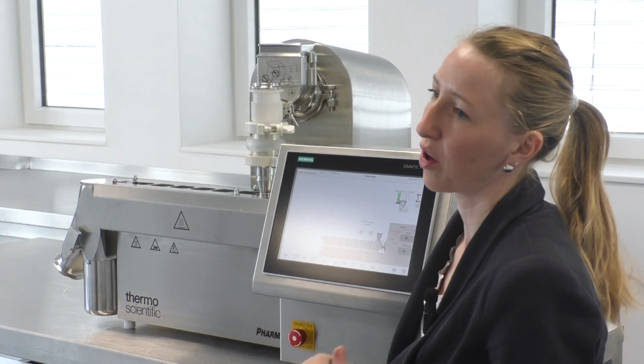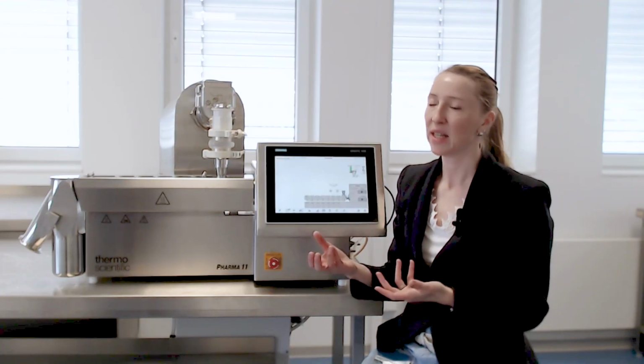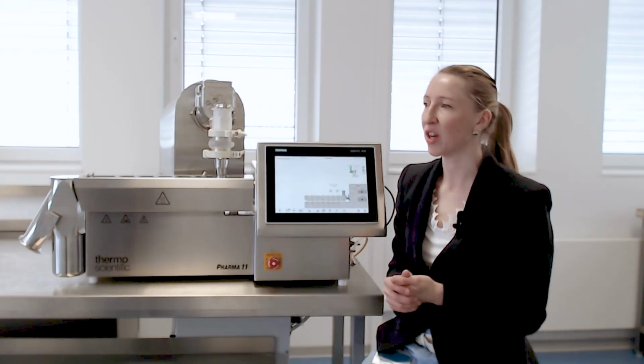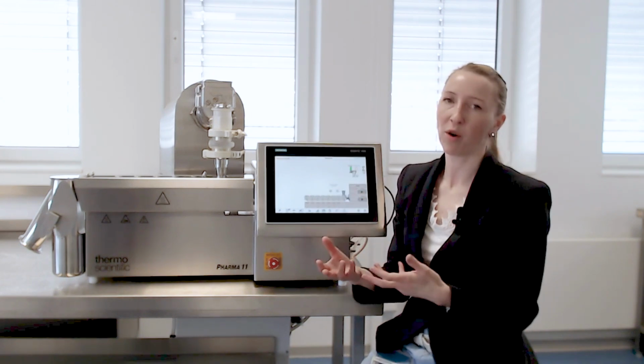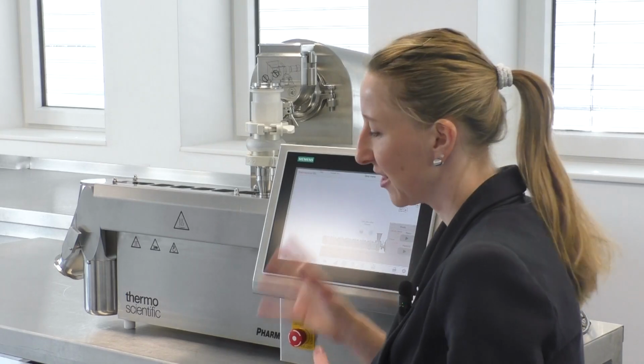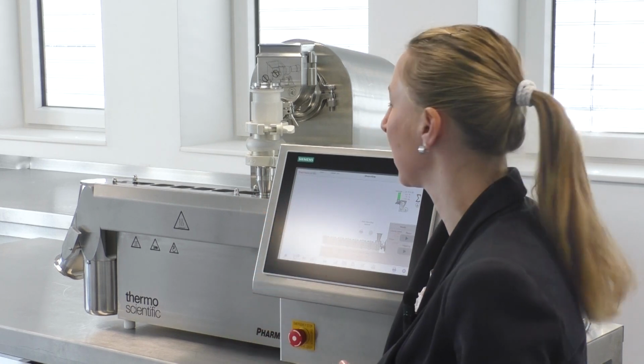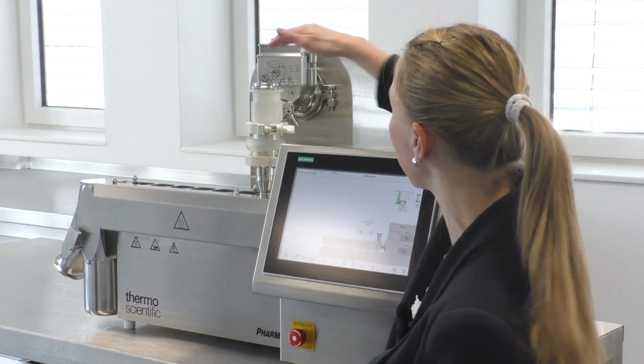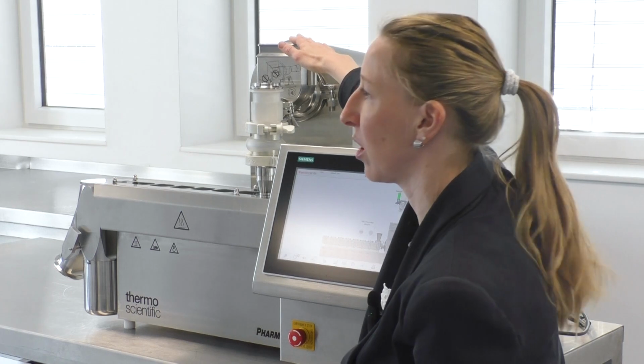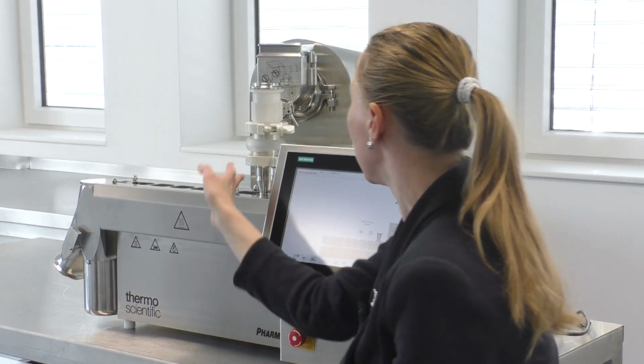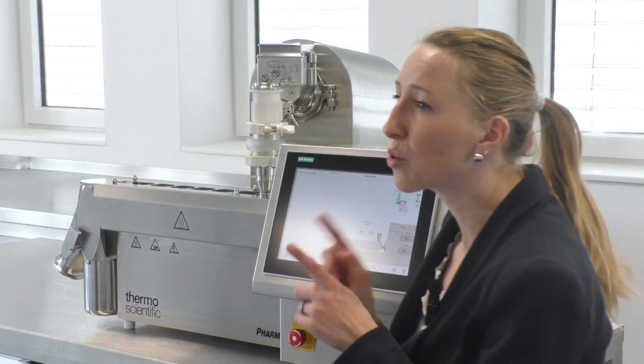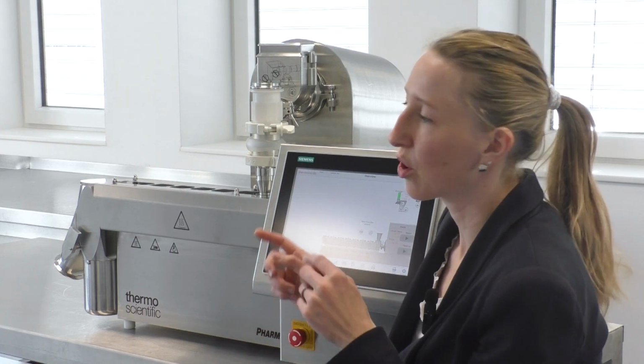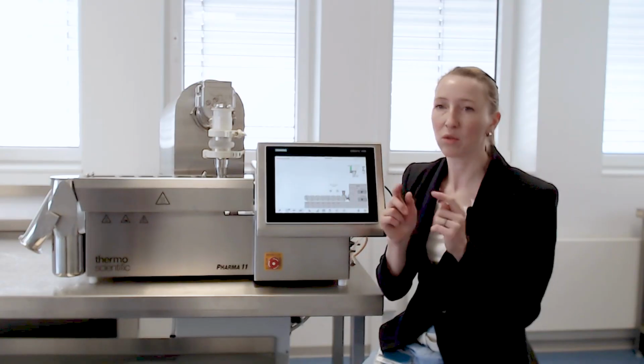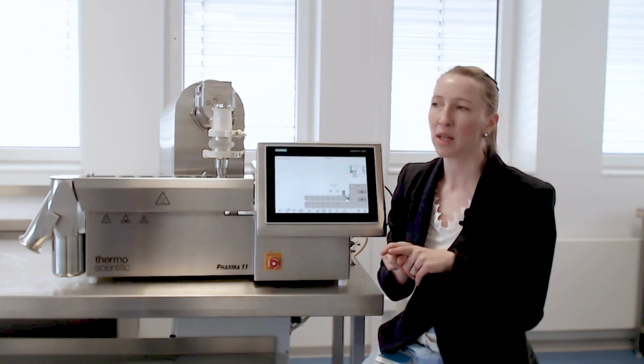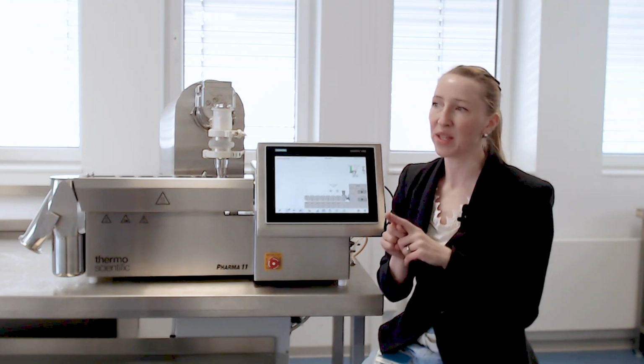Traditionally, TSG is for particle enlargement. So you would add water or any other liquid to perform this process. But in this really new dry amorphization process, we didn't need a liquid, so you only have one main feed using a gravimetric feeder. And then inside this barrel, we have two screws. These two screws turn in the same direction, so they are co-rotating, intermeshing. And with this, we have a very nice compounding effect.